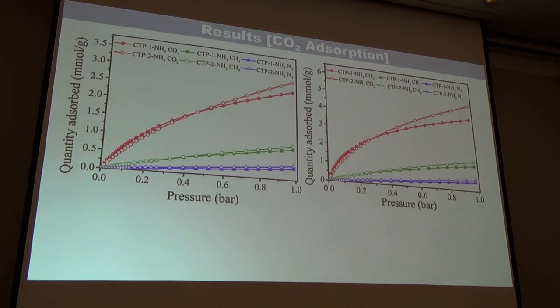Further, we have tested the single component adsorption isotherm at two different temperatures, 298 Kelvin and 273 Kelvin, for three gases: CO2, methane, and nitrogen. Here we can see these two materials are very much selective for CO2 capture. It is shown in the red line. CTP1 shows steep adsorption at the initial range, whereas the CTP2 material shows high adsorption capacity at the high pressure range. The steep adsorption at the initial range is because of the high nitrogen content, whereas the high adsorption of CTP2 at high pressure is because of its high surface area.